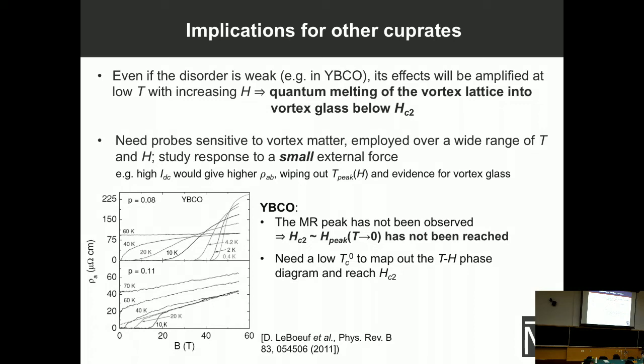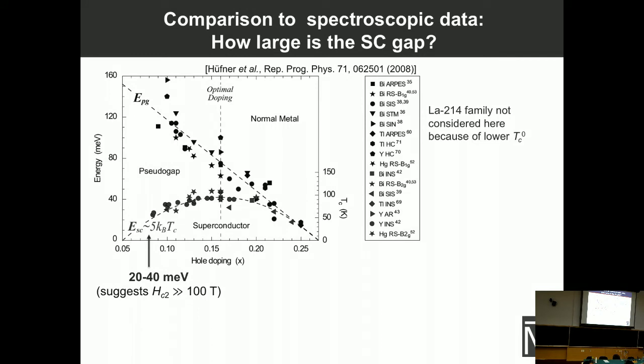So how do our results compare to other studies? Of course, as was pointed out more than once, this is an old field, and people have been trying to determine superconducting gaps in cuprates using all kinds of techniques. This is from a review paper from 10 years ago, and it shows the results from various spectroscopic probes like ARPES, STM, and so on for several different families of cuprates. You can see the results for the superconducting gap can all basically be described with this expression. The superconducting gap they found is 5 times the zero field TC. So for these materials, this is a much larger energy scale, which suggests indeed that the upper critical field may be experimentally inaccessible.